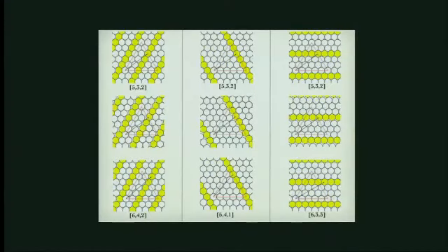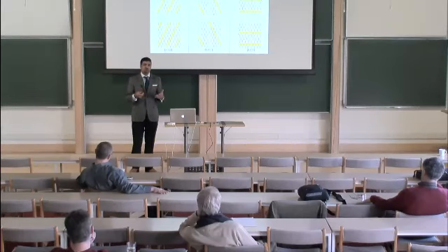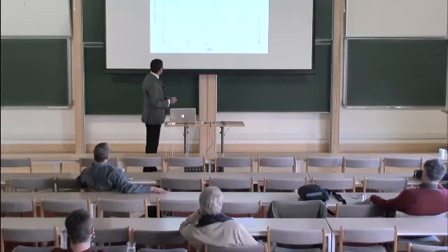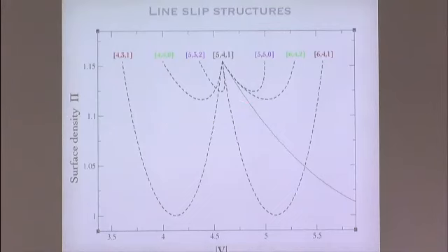The distances between, yes, that's right, and that counts for the fact that a different fraction of the lattice is being deformed, and therefore there will be a different relative change in the density depending on which line slip I choose to do. So if I show you the next one, here is, for example, the structure 541, and these are all the possible curves I have coming out from it due to these line slips. You can see the behavior is different, and that's because a different relative amount of the lattice is being distorted. Okay? This line here is my previous asymmetric global shear of everything.